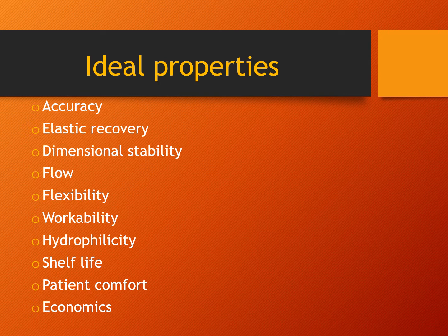And regarding flexibility, the polyether impression material tends to be the least flexible. That means it sets and becomes the most rigid of other materials. And this can be a problem when dealing with long and thin preparations of periodontally involved teeth. So there is a chance of fracture of the delicate gypsum dies due to the rigidity of the polyether material. So in such cases, reversible hydrocolloid, which is the least rigid of all materials, is the material of choice. That is when making impressions of multiple periodontally compromised teeth. So that is regarding flexibility.